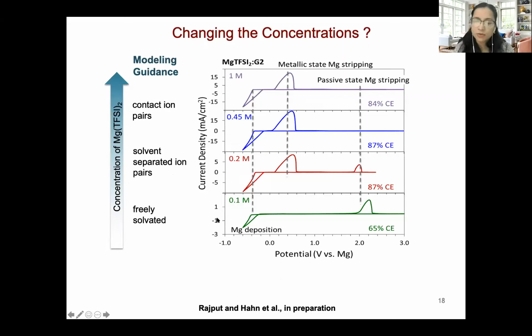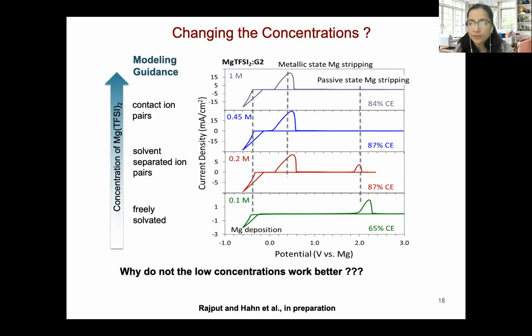And they came back to us with these results, which show that the electrochemical performance at very low concentration, where we claim that there are no ion pairs, is even worse. Okay, the performance actually deteriorates instead of improving. And we were wondering, why doesn't the low concentration work better? Okay, and that's a classic example of why experimentalists don't trust computational people. But we were surprised, because definitely at low concentration, there is no cation and anion pair formation.